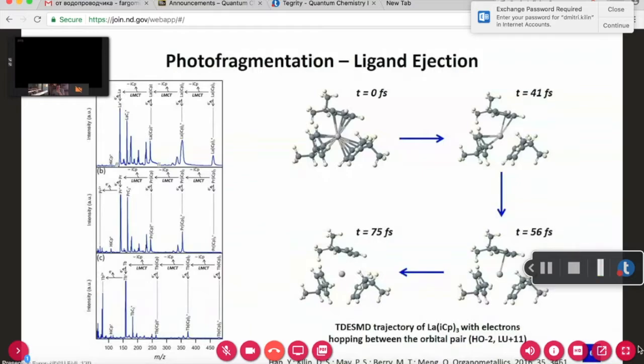Okay, so then is the oscillator strength relatively constant in time, or does it decrease as it starts to fragment? No, the oscillator strength is based on the geometry optimized structure. So it is fixed. But in the trajectory of TDESMD simulations, I guess this oscillator strength should be different, should change. Ideally, one should monitor the change of oscillator strengths and adjust excitations with time according to the change of the oscillator strengths. Okay. But for simplicity, as an approximation for short times, one chooses the oscillator strengths of the relaxed geometry, which is not as good the further away from the initial geometry we go, the worse this approximation is. Right. But it's easily optimizable, like if you do an experiment. Mm-hmm.